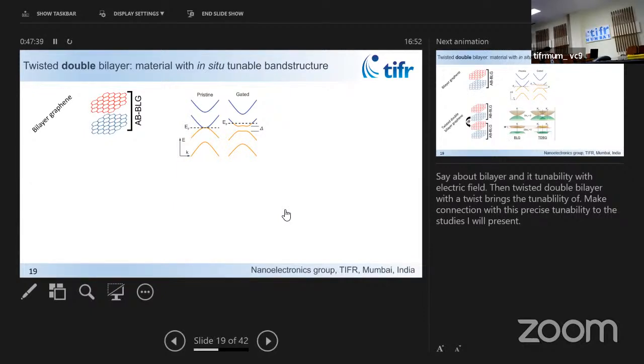So in the same material, you apply a perpendicular electric field, and you can make it a semiconductor, up to something like 150 milli-electron volts of band gap, as people have demonstrated. That arises from this simple idea that applying electric field makes the environment of this atom and this atom inequivalent, and that results in a band gap. And that's the starting system that we use in our experiments.